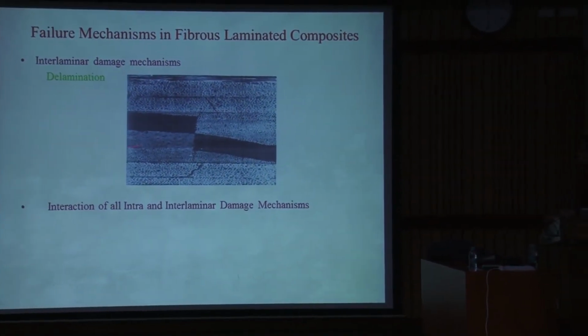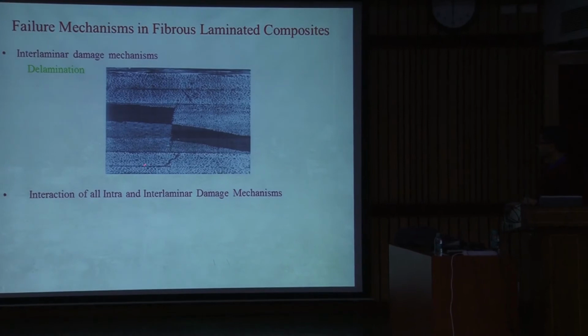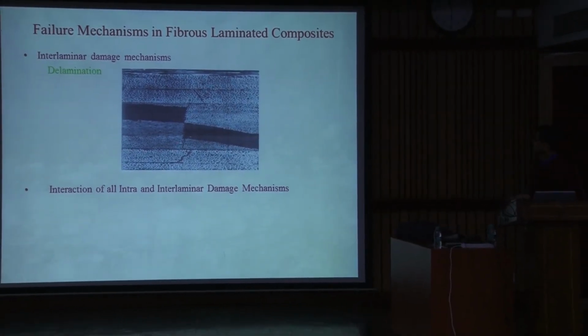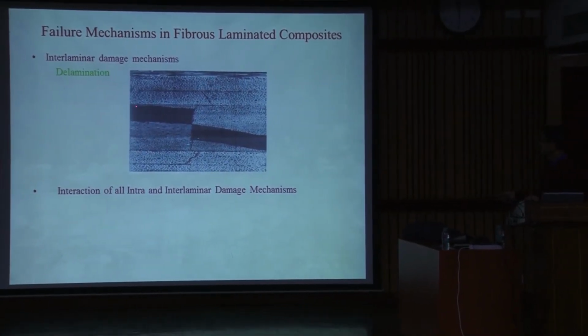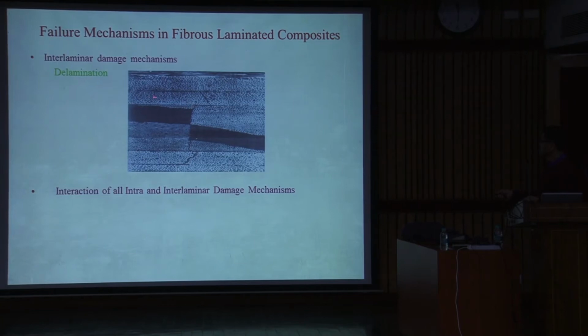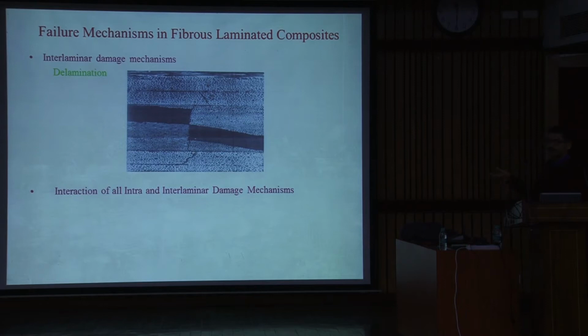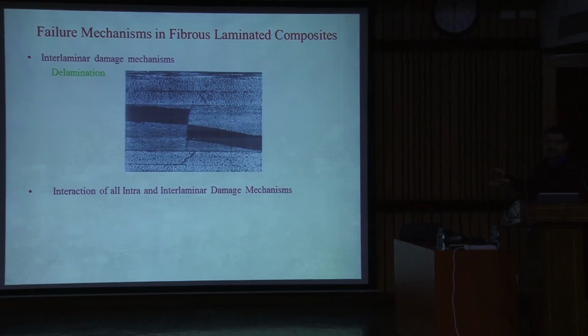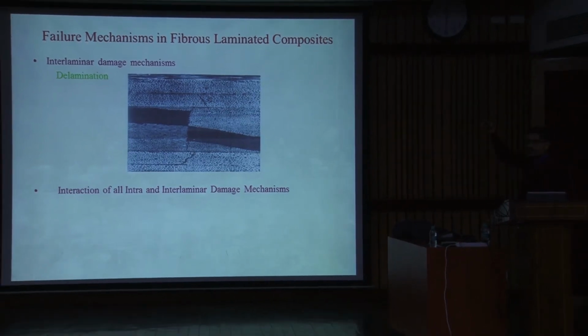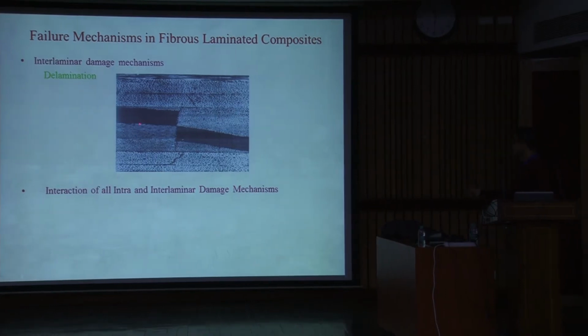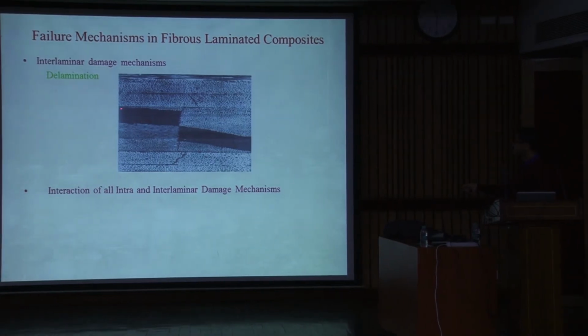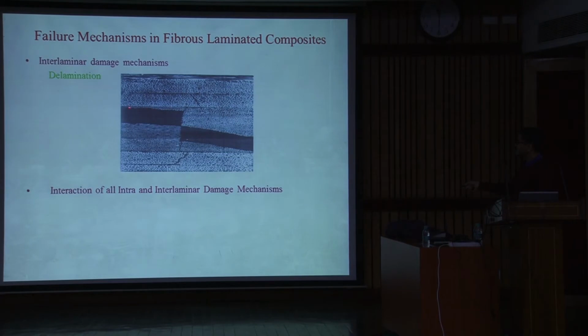So, this is the delamination. As I said earlier, there are many layers and what you see here is the interface between this ply and the next ply. This black region is nothing but these plies have been separated. They have delaminated and they have come apart. So the bonding between these two plies has become weak due to the loading or some reason, and then it is separated.